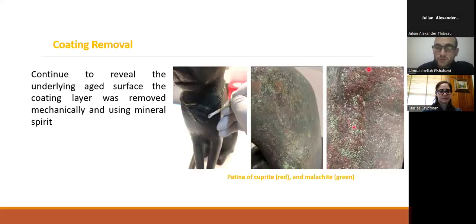The surface is dark, fairly even and shiny, not what we could expect from an ancient bronze. Closer examination, however, revealed some restoration suggesting that the 19th century restorer may have employed a rather aggressive treatment to produce an even surface. We can notice this from the surface here and the surface here after removing the coating layer.